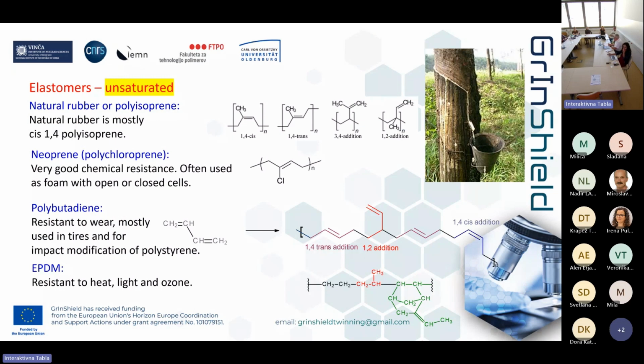There are elastomers, some unsaturated. These are, let's say, natural rubber or also synthetic polyisoprene, caoutchouc. Natural rubber we get from the trees, but we can synthesize polyisoprene, which has many similar properties to the natural product. There is neoprene, which is polychloroprene, which has very good chemical resistance and is used also for some foams. Polybutadiene is resistant to wear, and that's the polymer used mostly in tires for that reason. Although also in tires you see different layers made of different rubbers, and each layer has its own function there.